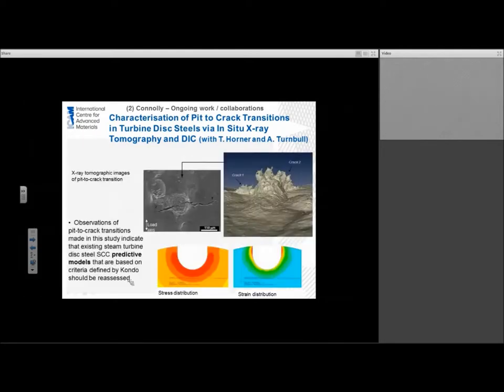We went on to look at some in-situ work and we take a look at a pit with two cracks emanating from it in the SEM image. If we look at the corresponding x-ray tomography attenuation data, what we've done here is we've basically inverted the material and we're just imaging the surface of both the bulk material, the pit, and the cracks. We're basically doing a very high resolution replica. If we take a look at the tomography, we see initiation again at the mouth of the pit, not at the deepest part of the pit. The second crack more than likely has initiated at the mouth and has grown to grow further than the pit depth itself.